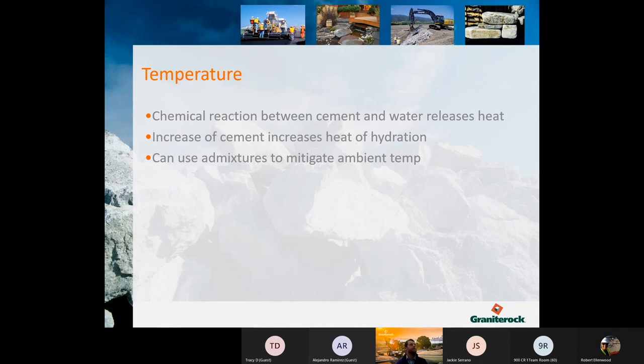Another property of concrete is the temperature. Like we talked about, when the cement touches water, that's a chemical reaction, and that does release heat. Whenever you increase the cement, it increases the heat of hydration, so the heat from that chemical reaction. And also, like we talked about, we can use admixtures to help mitigate ambient temperature. Because the cement is a chemical reaction, the hotter the ambient temperature, the faster that reaction takes place. So we can play with admixtures to mitigate that.